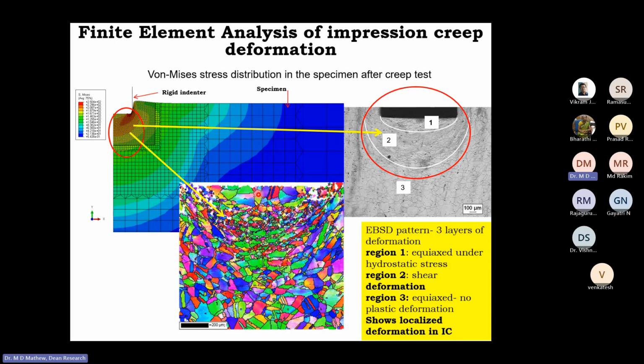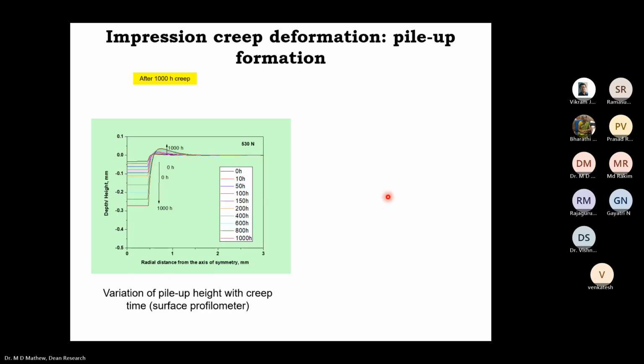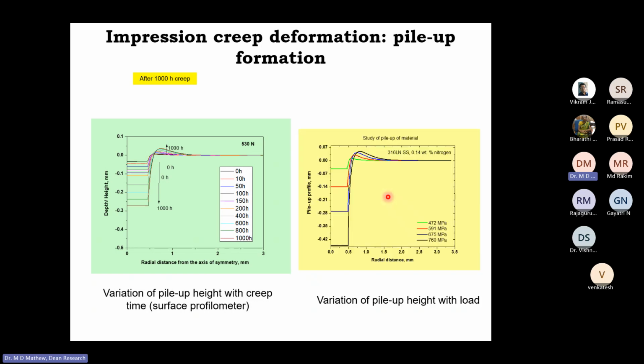So here you have equiaxed grains, under that all the elongated sheared grains, and then the material under that is again equiaxed with no plastic deformation. So if we look at the material under the indenter in an impression creep test, you will find these three different patterns describing the kind of deformation that has happened. And another thing, of course, there will be the pileup of material, because as the indenter goes inside the material, it has to be accommodated either by the material surrounding the indenter, or some of it will have to be thrown out in the form of a pileup. And you can always measure that using a surface profilometer and then derive a lot of information from that, both as a function of time as well as a function of stress.